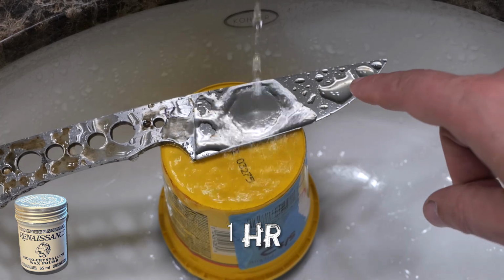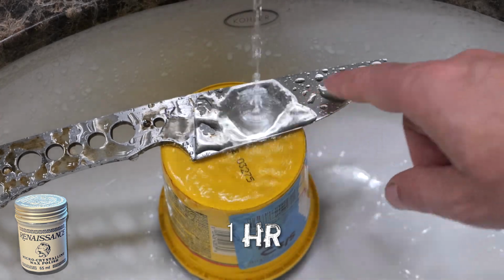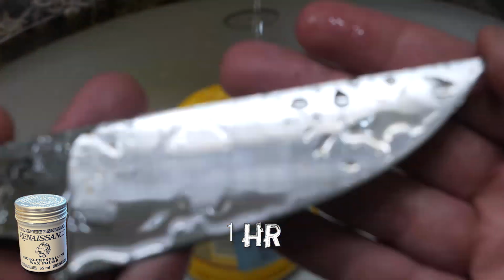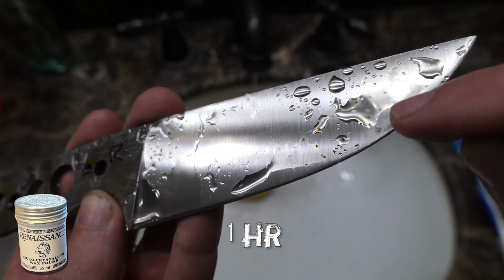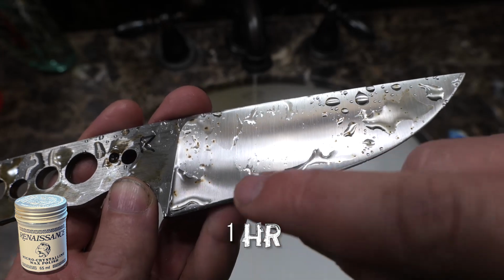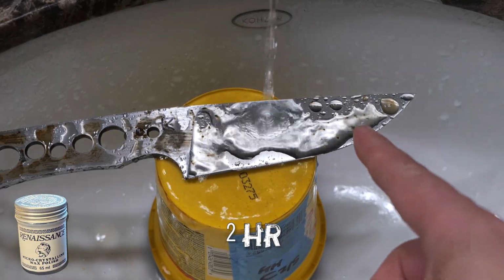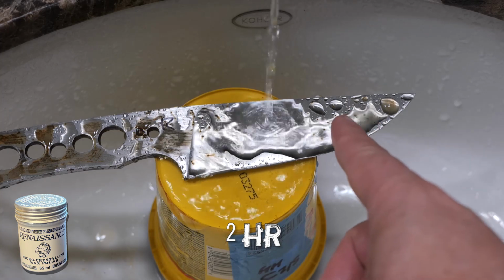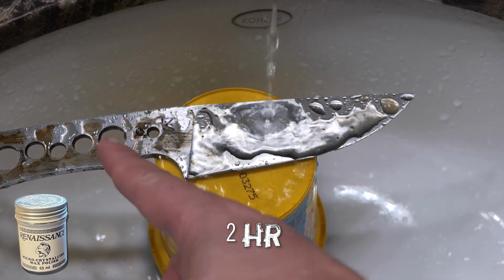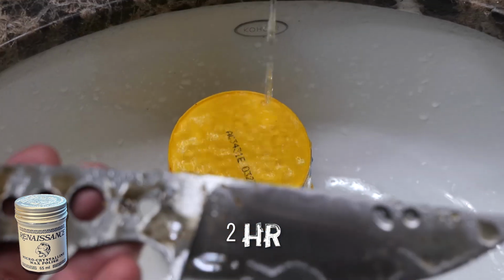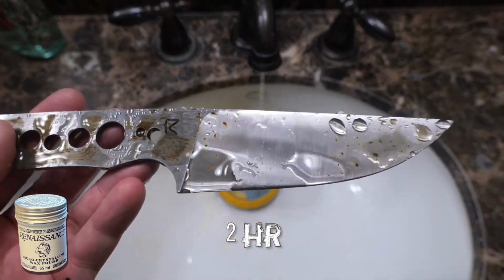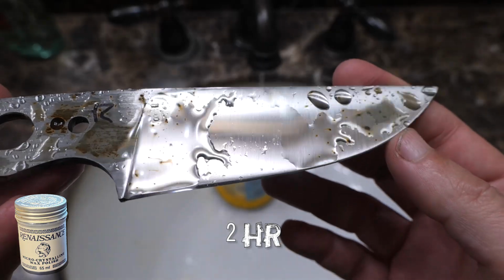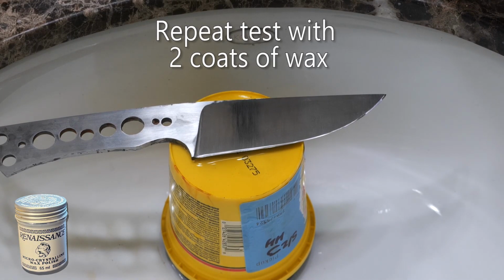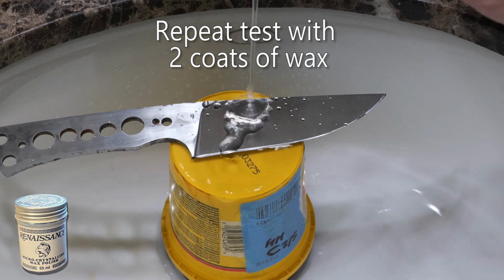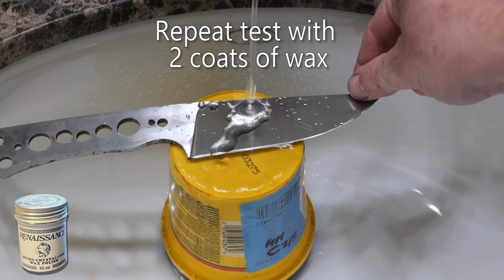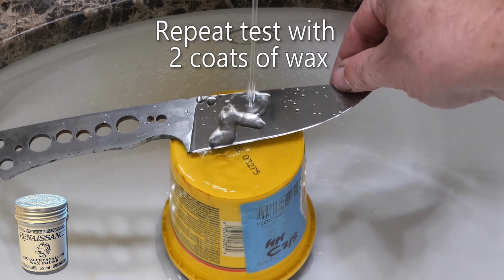So at 1 hour, you can already see some rust spots forming here, here. We're at 2 hours now. The Renaissance wax portion is only doing marginally better than the bare portion. Renaissance wax. I couldn't really believe how poorly that did, so I went back, started over, and this time we did two coats of Renaissance wax, and that's what we'll do for all the testing from here on out.